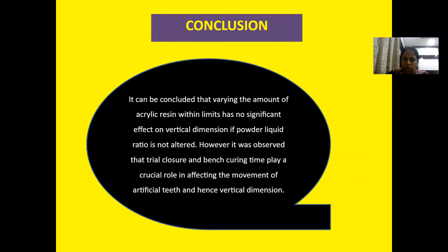Finally, I would like to conclude my topic. It was observed that varying the amount of resin within limits has no significant effect on vertical dimension if the powder liquid ratio is not altered. However, it was observed that trial closure and bench curing time play a crucial role in affecting the movement of artificial teeth and hence the vertical dimension. Thank you.